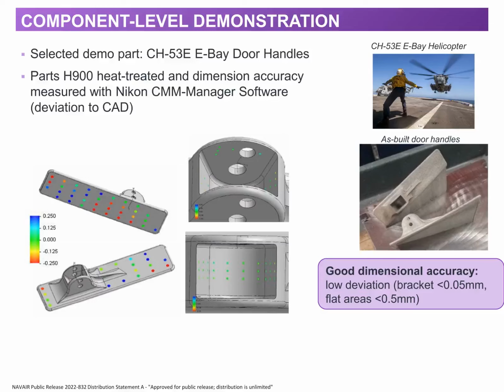QuesTek has been able to demonstrate the printing on a component level demonstration part. We were able to print CH-53E E-bay door handles, and the parts were only aged at H900, and then we verified the dimensional accuracy. So not only were we able to meet the strength requirements, but we also verified that the component was able to meet dimensional accuracy in the as-printed and aged condition.